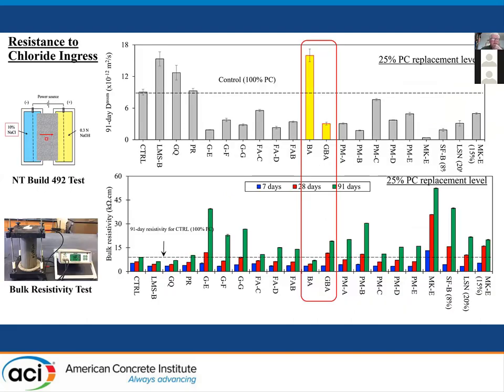Again, this is the 91-day non-steady state migration test using the NT Build 492 test on the top and bulk resistivity on the bottom. And the bottom ash and the ground bottom ash are shown there. So you get much better results, and once you grind the bottom ash, it's as good as the fly ashes over here on the left. And the bulk resistivity is equal to or better than the fly ashes as well at the same replacement level.